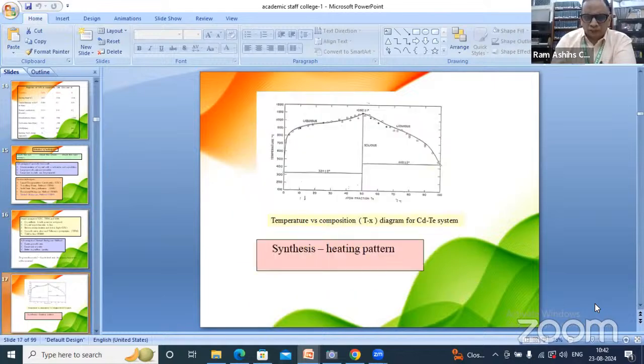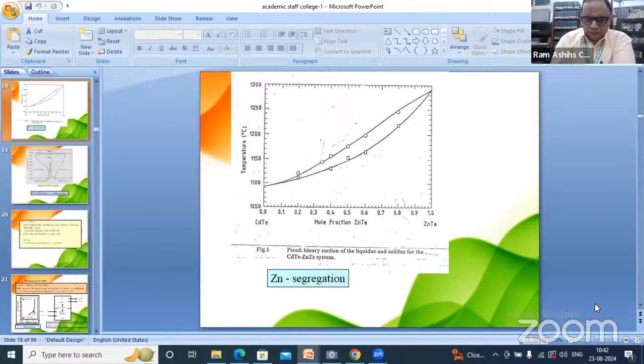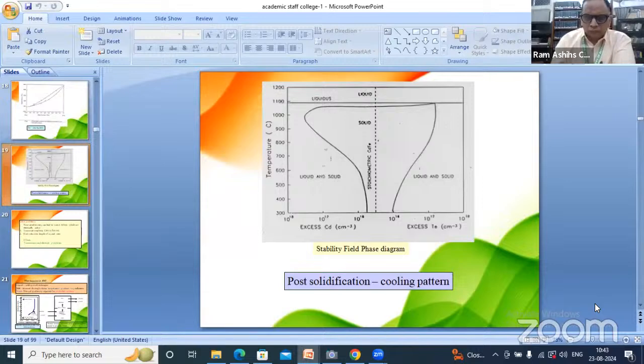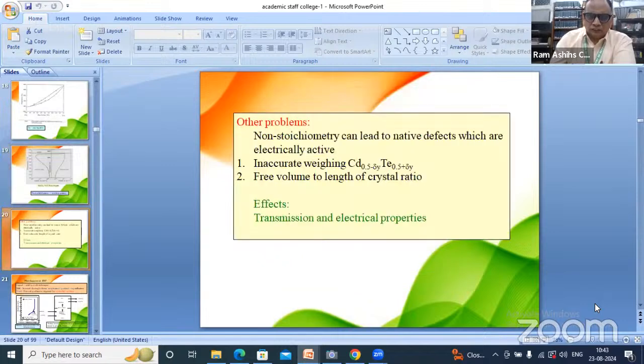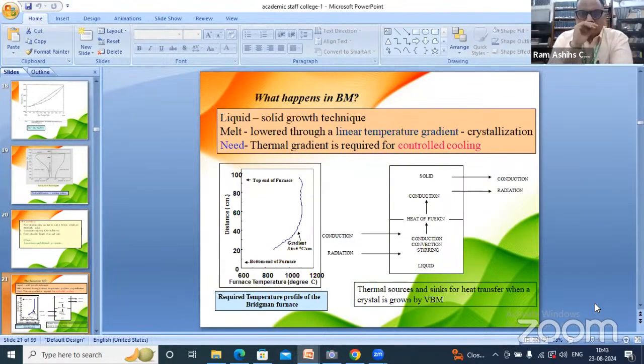This is the phase diagram of the crystal growth technique, where a thermodynamics study is required. This is the theoretical phase diagram of the pseudo-binary section of the liquidus and solidus for the cadmium telluride-zinc telluride system. This is the post-solidification cooling pattern. By these three theoretical things, we optimize our parameters, and with these things we grow the crystal. This is the required thermal profile of the furnace, and from the constant zone to the gradient zone we are moving from top to bottom.